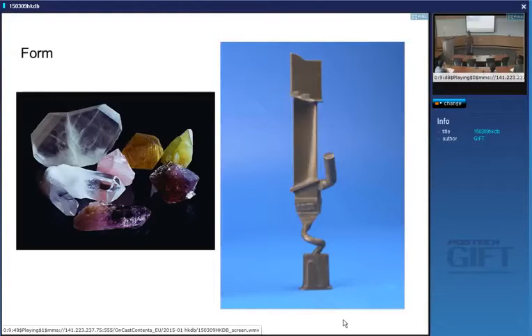So, for example, this is a single crystal, right? Do you recognize what this is? It's a turbine blade for an aircraft engine to work in the very high temperature region of the aircraft engine. And this part of it is a single crystal. Okay? It's made out of a nickel alloy. And what you do is you start solidification from here, and you're solidifying in a temperature gradient, so you get lots of crystals growing in this direction, and the one that is growing fastest fills up this spiral and blocks all the others. And therefore, the rest of it solidifies as a single crystal. Why do we need a single crystal for something that's operating at a very high temperature, something like 1400 degrees centigrade, and rotating extremely fast? Why do we need that?